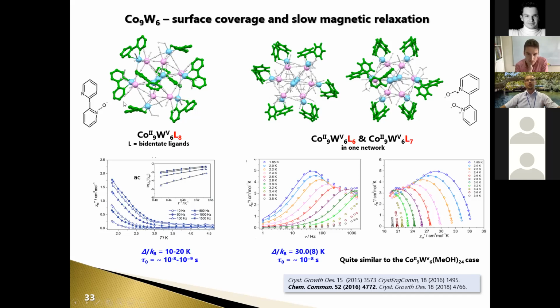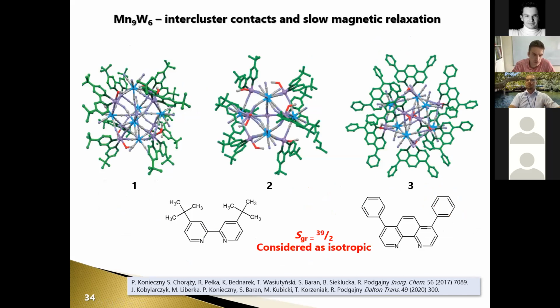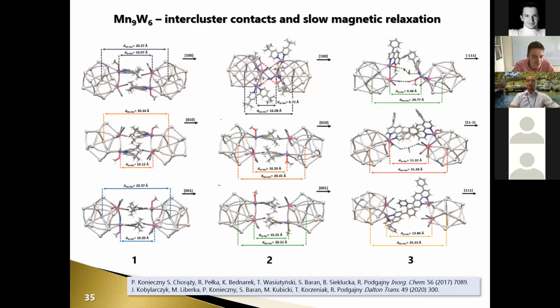This is in opposition to the other ligands where we have the 8 coordination. And only for this one, we have also notable slow magnetic relaxation with the barrier of about 30 K, quite similarly to the original bimetallic cobalt tungsten clusters. We observed also some field-induced slow magnetic relaxation on tungsten manganese cluster, which are supposed to be rather isotropic as far as the ground state is concerned.